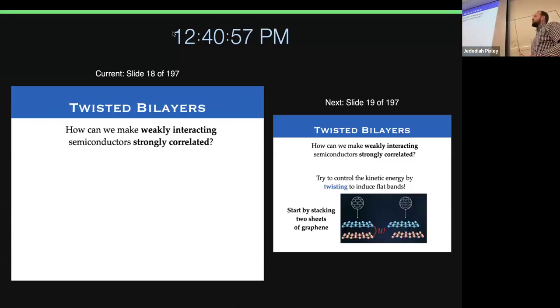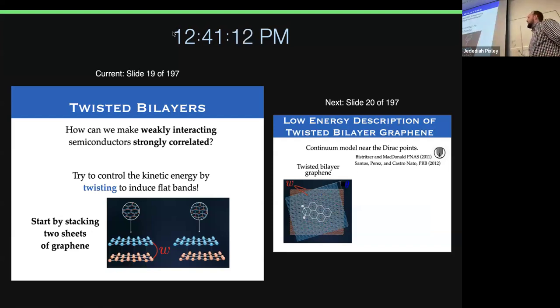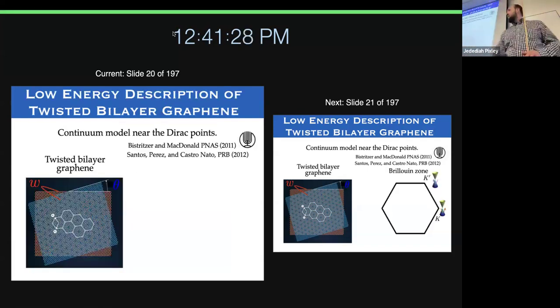So the cornerstone for this came with twisted bilayer graphene. And it was basically taking weakly interacting semiconductors and asking how do we make them strongly correlated? And so let's start by just putting them together. So if we stack 2 sheets of graphene, the low energy configuration is so-called Bernal stack graphene, AB stacking. I'm showing that here, that's the low energy configuration. And when you bring them together, they start to tunnel with a strength W. But in reality, the experimentalists could have also aligned it and twisted it and put it down at an angle. So in addition to the tunneling, now we have a twist angle.